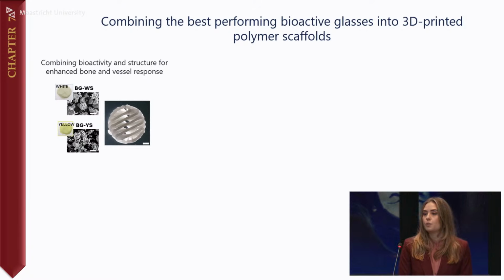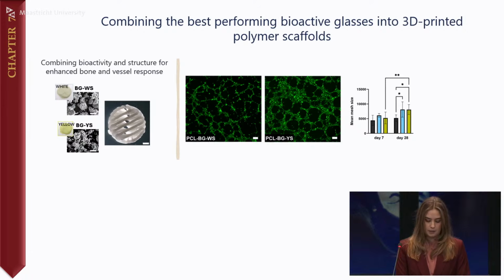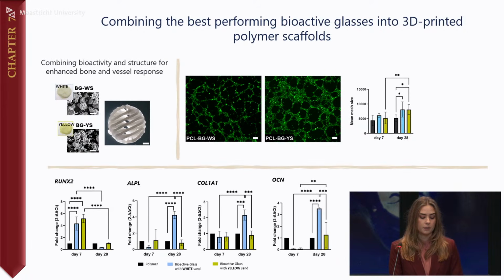After identifying which bioactive glasses performed best, that was bioactive glass synthesized with white sand and yellow sand, we decided to take a next step, that was combining these glasses with a polymer. The idea here was, again, to combine the bioactivity of glasses with structure and flexibility of polymer. And the composite materials that we obtained were able to stimulate both bone and vessel-forming activity.